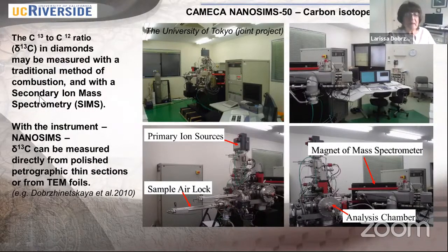So NanoSIMS is nano secondary ion mass spectrometry, and it came to replace the traditional method, combustion. You make a combustion of the mineral, then you have the carbon in this combustion product, and then you measure the isotope. But here we have the opportunity to put your thin section with your diamond, with your small inclusions inside, and study in detail from place to place the carbon isotopes to understand their homogeneity. The delta 13 ratio to 12 is the main characteristic, known as delta 13 carbon isotopes in diamond.